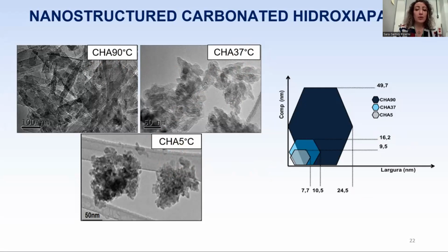Electron micrography shows that the morphology and the primary particle size are completely different and temperature dependent. So hydroxyapatite synthesized at 90 degrees shows a more elongated and probably crystalline morphology, because the image seems to be more defined.